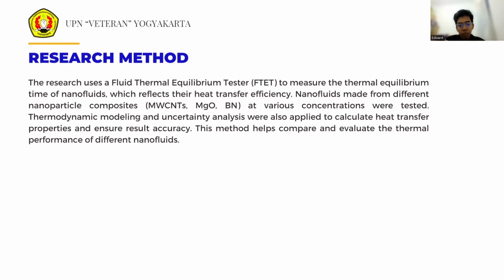Temperature sensors were placed in both cylinders, and data was logged continuously to monitor the temperature changes. The time taken for the system to reach thermal equilibrium, where the temperature of the nanofluid and the water equalize, was recorded as a key metric for assessing the thermal efficiency of the nanofluid.